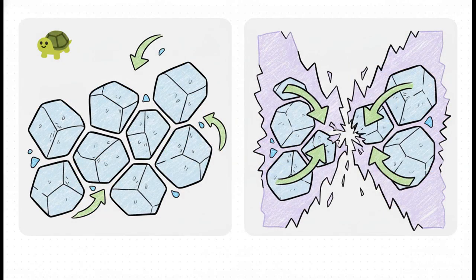Boom, you achieve a fully dense, solid ceramic. But hold on, the battle is definitely not over just because the heating stops. How you cool it down is absolutely crucial. If you cool the ceramic slowly, that trapped oxide liquid actually has time to pull back into isolated little pockets. This allows the clean aluminum nitride grains to directly touch each other, creating a high-speed highway for our heat phonons.